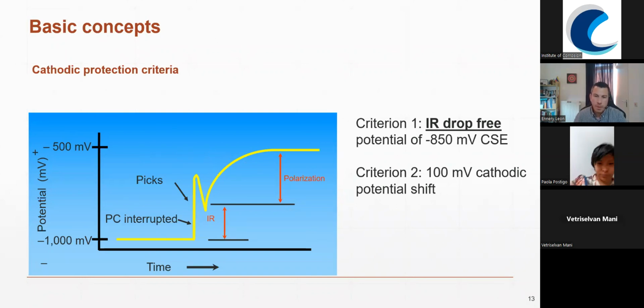of this peak. And we also have a second criterion, that is the 100 millivolts cathodic potential shift. It's also considered that a structure is protected when there is a minimum of 100 millivolts of cathodic polarization between the structure and the reference electrode. And this criterion is used, for example, for the tank's bottom, where it might be challenging to reach minus 850 millivolts. The 100 millivolts could be easier to achieve.